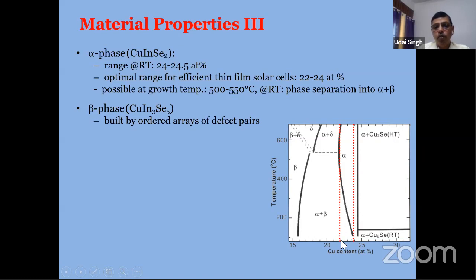If you go below this, less than 22%, you are going to generate certain defect states. The best range is around 24 to 24.5 atomic percent of copper. For the optimal range, you can get efficiency between 22 and 24. So while growing this material, one has to be very cautious. Copper should be between this, at a possible growth temperature of 500 to 550.